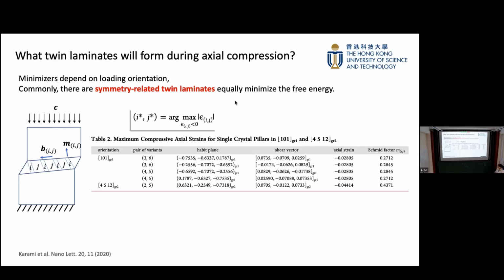Actually, that also showed in the previous slides in the single crystal copper aluminum nickel. We see twin laminates branching into austenite. Yeah, but really near. Nobody really looks at the transition layer. That's what I'm asking. That's very hard experimentally. Yeah, but macroscopically we do see the twin laminates.